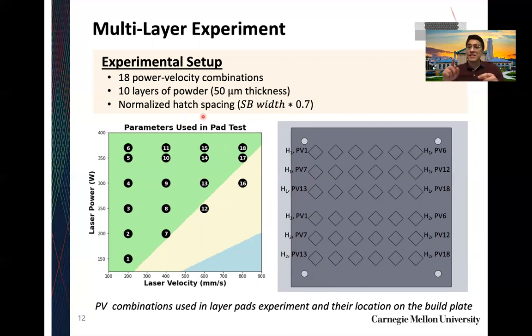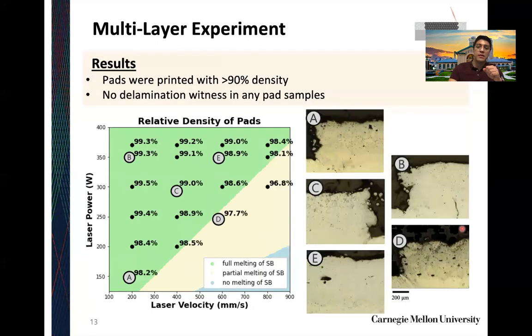And the hatch spacing, or the spacing between the rastering of the laser, was a normalized hatch spacing where we multiplied the respective single bead width of each parameter set by 0.7. And of course, we stayed true to our layer thickness of 50 microns. And for this experiment, we actually did 2 pads for every power velocity combination, as you see here on the right, for a total of 36 pads.